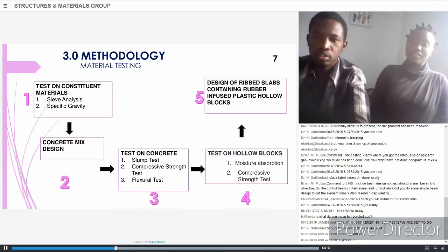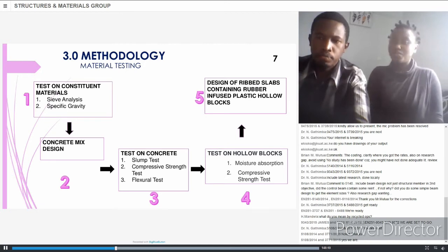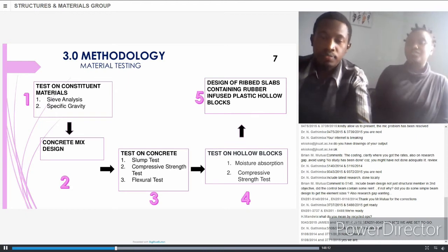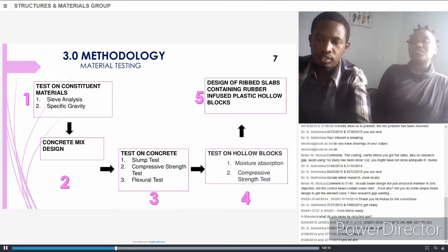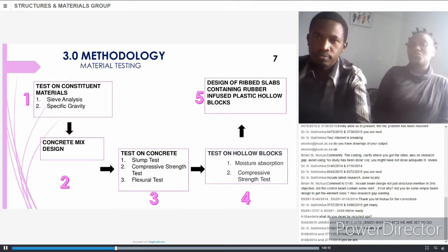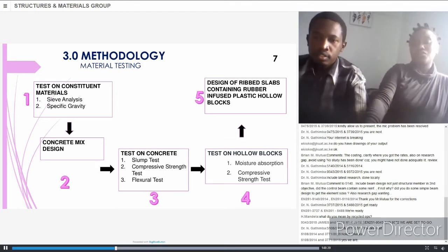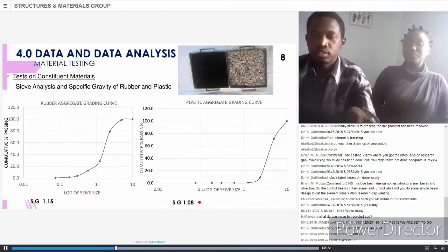On the concrete itself, we did the slump test, the compressive strength test, and the flexural test in line with the standards. And then we had tests on the hollow blocks after we achieved the optimal mix. So we conducted moisture absorption and compressive strength tests on the hollow blocks themselves. And afterwards, we designed a ribbed slab containing the rubber-infused plastic hollow block and also the control hollow block.